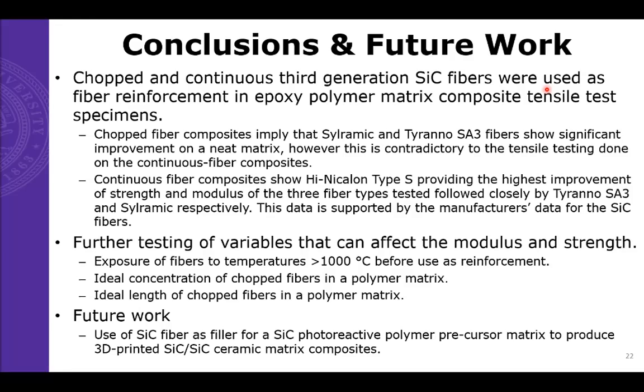Further testing of the variables we'd like to conduct would involve how they might affect the modulus and strength, such as exposing the fibers to temperatures above 1000 degrees Celsius before reusing them as a reinforcement, as well as the ideal concentration and length of chopped fibers in a polymer matrix. We're also going to be performing future work using silicon carbide fibers as a filler for a silicon carbide photoreactive polymer precursor matrix in order to 3D print a ceramic matrix composite and see how well that works.